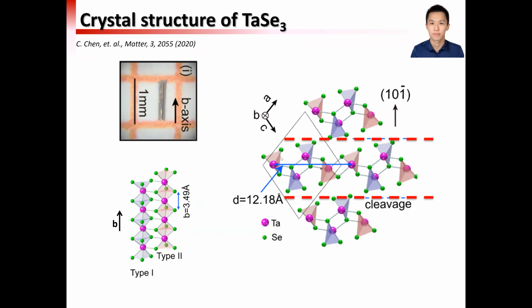On the right-hand side, I show the cleave plane. The tantalum triselenide chains organize themselves like packed chocolate bars, exposing an atomically flat surface. However, since it is quasi-one-dimensional, the cleave plane is pretty rough. That's why we need to use micro ARPES, taking advantage of the small beam spot, so that we can get a relatively flat surface of this material.